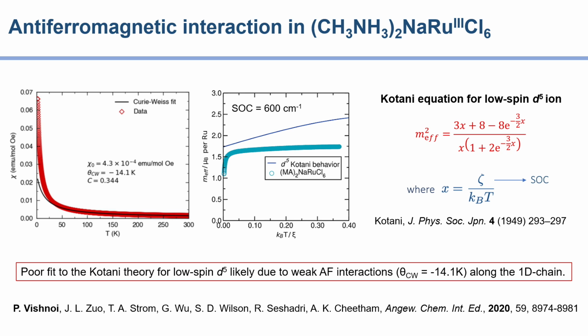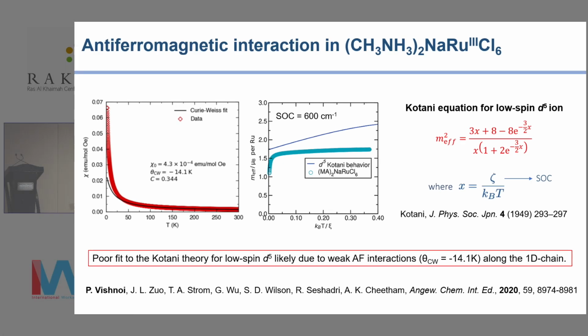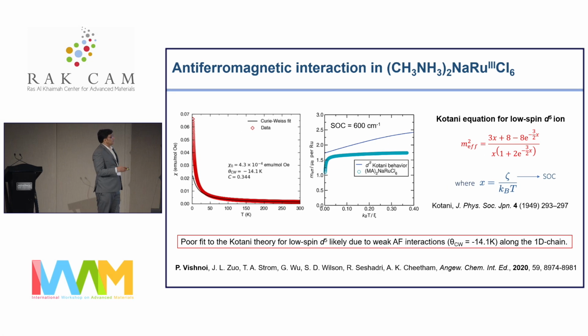And let me mention that this Kotani equation is designed for a system which has a metal complex, the magnetic metal in 6 coordination, perfect octahedral, and that doesn't interact. So a non-interacting magnetic system is the primary criterion for this. So the deviation that we see is primarily because of this antiferromagnetic coupling. However, we can have an approximate value of spin-orbit coupling strength that is about 600 inverse wave number.